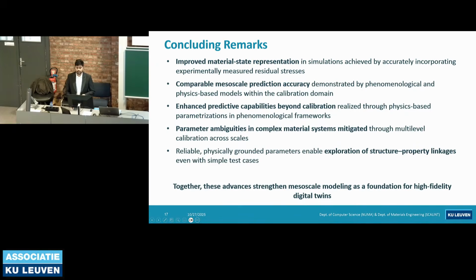But damage, yeah, this method is also quite different from finite element, where usually if a cell is fully damaged, it is deleted out, so you have a void. But in this case, we cannot have empty material because the solver requires it to be periodic. So we can have an elastically very compliant material, but there are limitations for this method, and voxelization is one of the limitations.